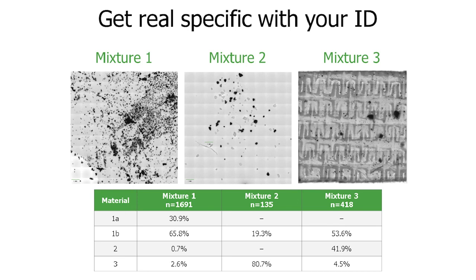Of the 418 particles that were identified from this sample, about half were material 1B, just under half were material 2, and a small fraction, under 5%, were material 3.